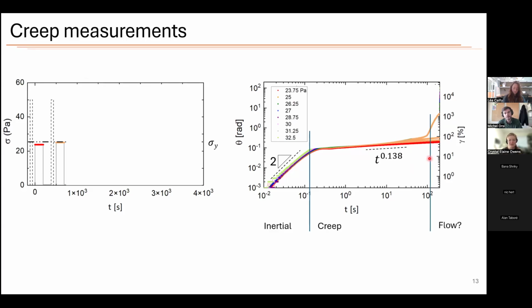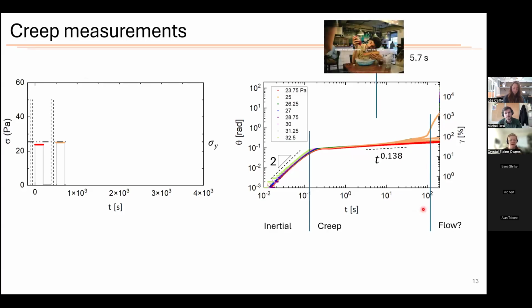And then maybe it looks like we have hints of some flow after you get a couple minutes through the test. And we can keep in mind the 5.7 seconds that we were thinking about earlier. Clearly, if you apply too little stress, this would be equivalent to having only a very small amount of ketchup in the bottle that's flowing under gravity. Then you are missing the 5.7 second mark.